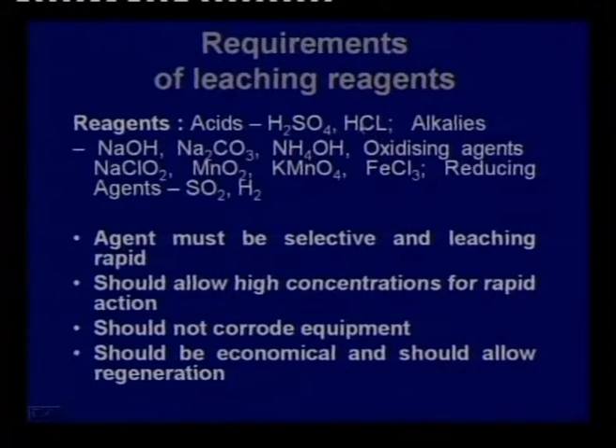Now, essentially in hydrometallurgy we need a concentrate which will be leached. During leaching, generally we take the metallic values in solution and the gangue is rejected in the solids, but the opposite of that is also done. We saw in the case of monazite leaching by alkali in our country, alkalis dissolve away the undesirables, the desirable part remains in the insoluble residue. In the case of aluminum, alkali leaching takes the aluminum value into solution, the iron that we do not want to come in the leach liquor is separated as a solid residue. So, leaching does not mean taking metallic value in the solution, it can take the metallic value preferentially in the residue also.